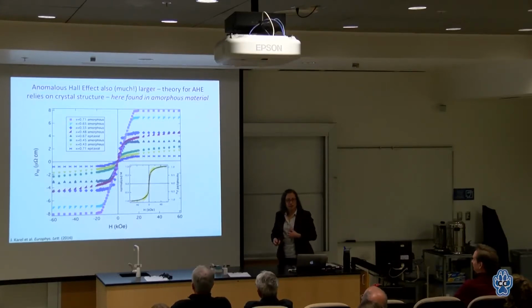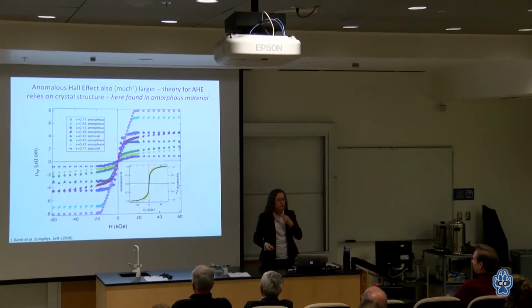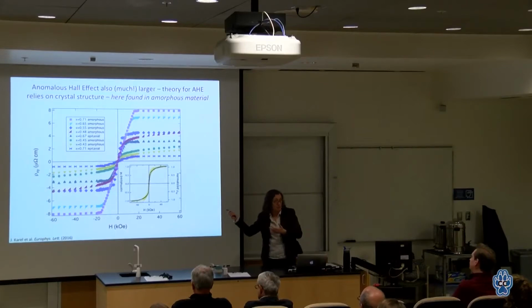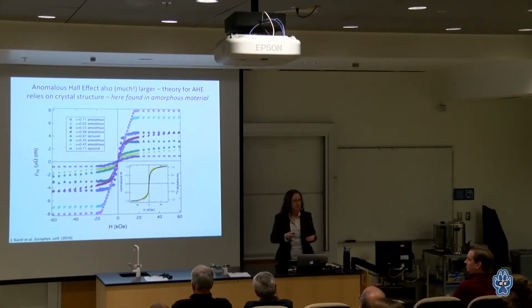And perhaps even more interestingly, getting back to my very first point, all the descriptions of the anomalous Hall effect in the crystalline materials rely on this perfect periodic structure. But we're seeing the same effect. In fact, in some ways, it seems larger, depends what you normalize by. But we're seeing it in a non-crystalline material.